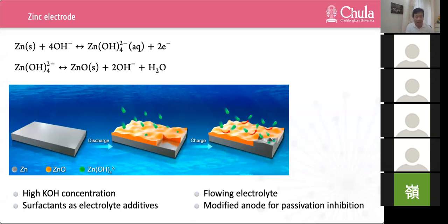Therefore, to mitigate the impact of passivation on the charge and discharge performance of battery, zinc passivation of zinc air battery can be eliminated or decreased by the design of metal anode materials and modification of electrolyte composition. Well, zinc electrodes are in close contact with the electrolyte. So the zinc electrode passivation can be inhibited by modifying or adjusting the electrolyte composition. So in general, there are many approaches to suppress the zinc oxide passivation layer, such as improving the electrolyte concentration, adding surfactant to the electrolyte, and producing liquid flow to dissolve or destroy the dense structure of passivation layer.